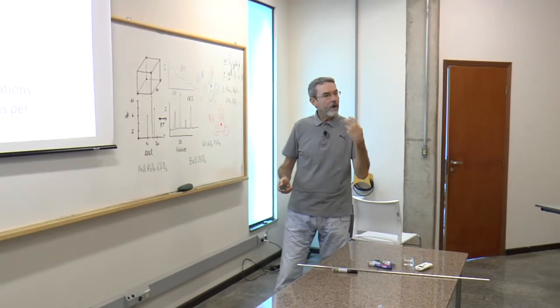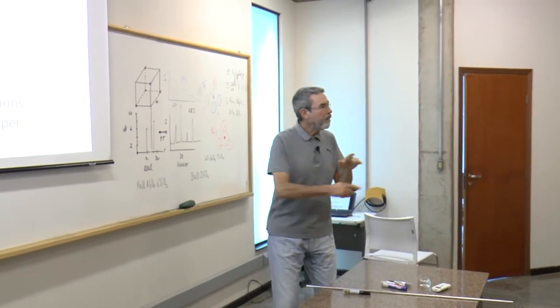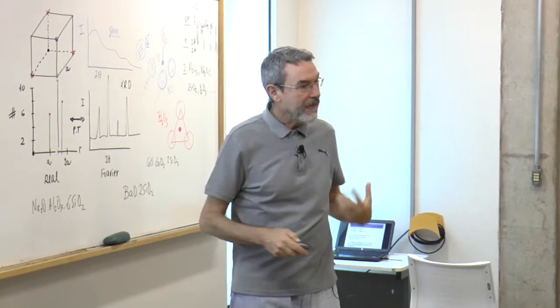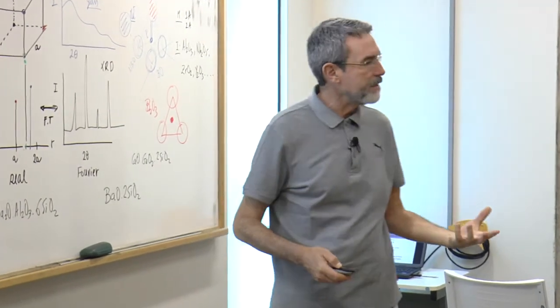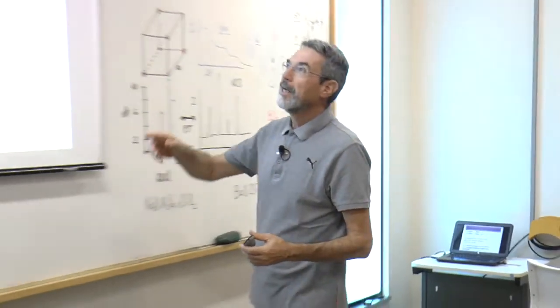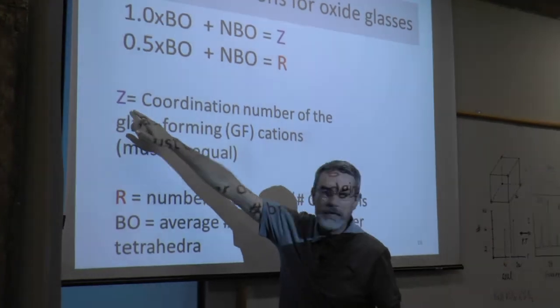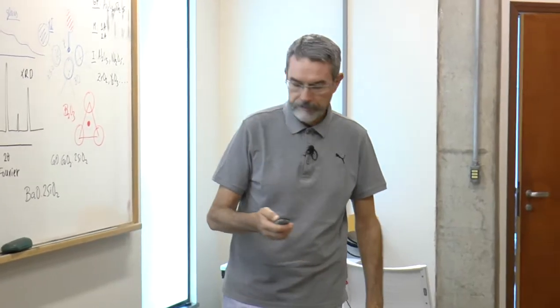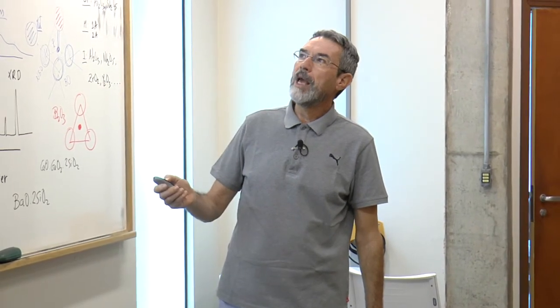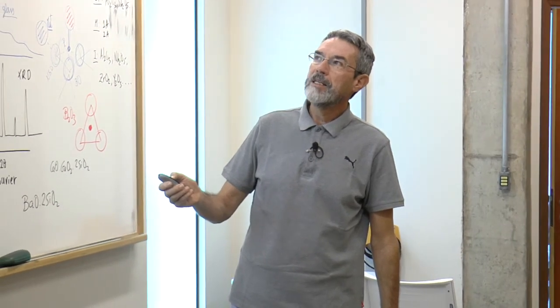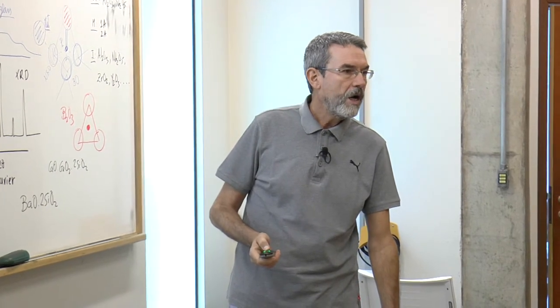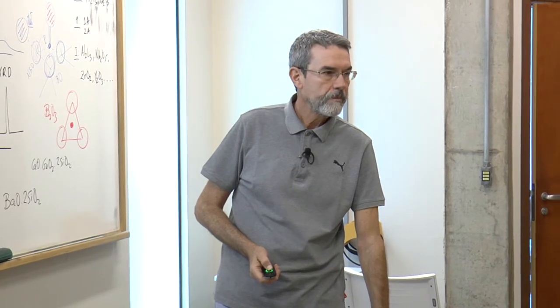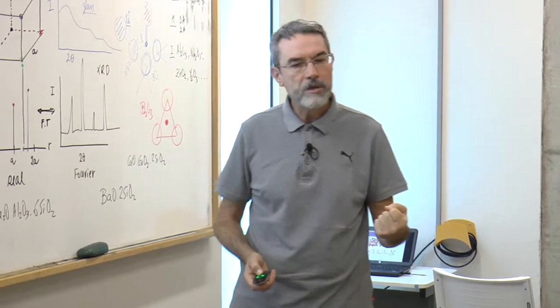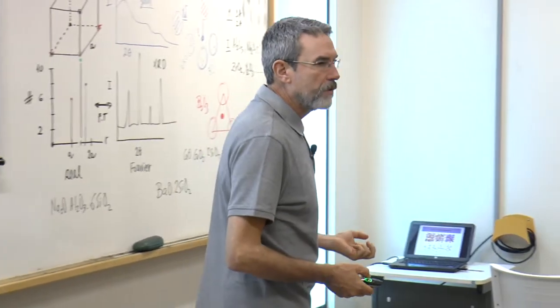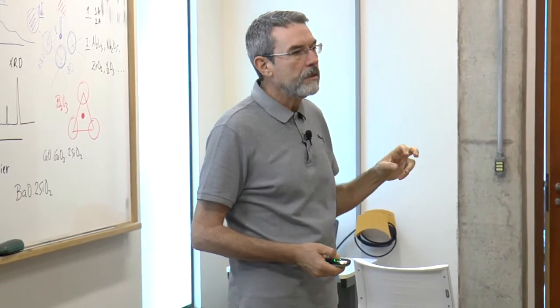Right. So this is a way to calculate the average. The problem is that there is a distribution, but the average can be calculated by knowing the chemical formula of your glass, for any glass, as long as the glass-forming cations have the same Z. You cannot mix cations with different Z's, because then this formula does not work. So this is the idea of the Qn. The n here is the average number of bridging oxygens per tetrahedron. You can take this measure from NMR or from Raman spectroscopy. Raman spectroscopy and NMR can give you a measure of n.